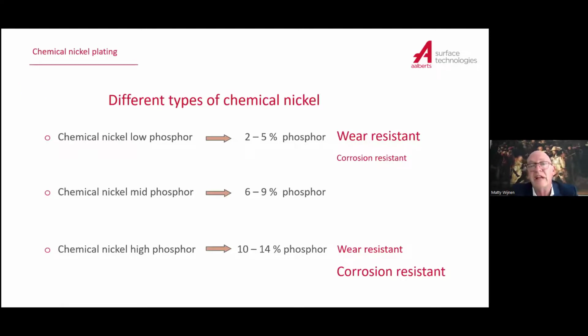In principle, there are three different types of chemical nickel. You have chemical nickel low phosphor, chemical nickel mid phosphor, and chemical nickel high phosphor. The percentages I put there behind. The chemical nickel low phosphor is mostly used for wear resistance. That means with 2 to 5% phosphor, you have a real crystalline structure of your coating, which will give you a good wear resistance. Due to the crystalline structure, you have, of course, crystal borders, and those crystal borders are susceptible to corrosion. So the corrosion resistance is less.